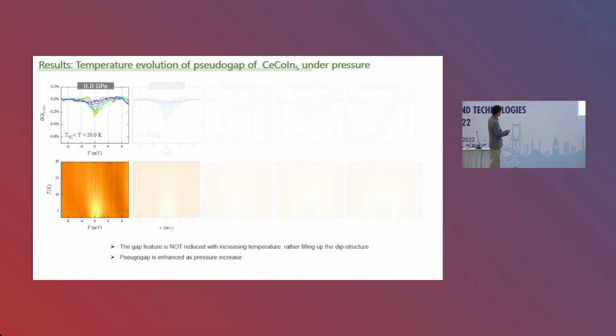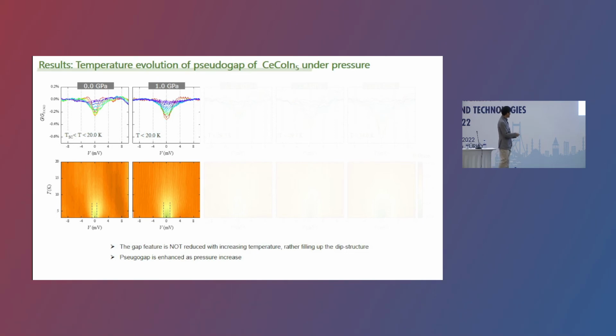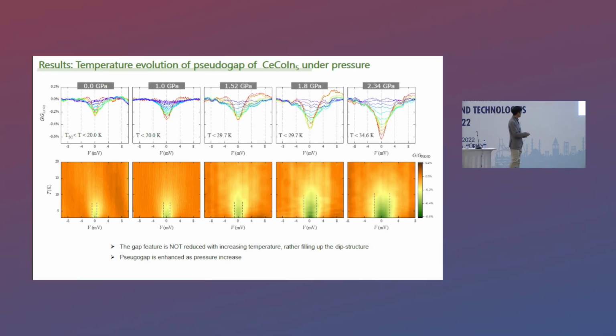At ambient pressure, this is the color contour plot of temperature as a function of bias voltage. You can see that instead of the gap being suppressed with increasing temperature, it is pretty much insensitive. With increasing pressure, you can see that the size of the gap is enhanced, the pseudogap is enhanced, and the T_g is also enhanced. You can see a similar trend: the size of the gap increases, but it more or less fills in with increasing temperature, and the pseudogap temperature increases with pressure.